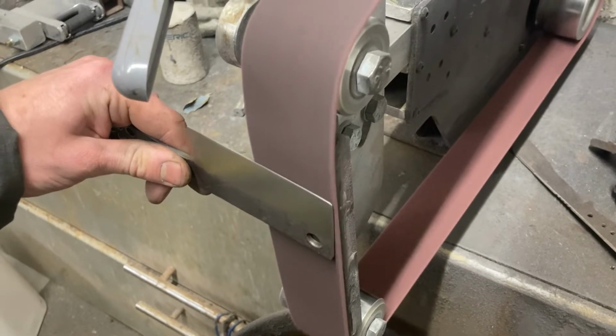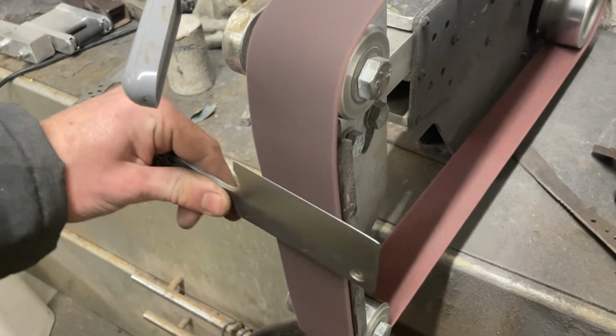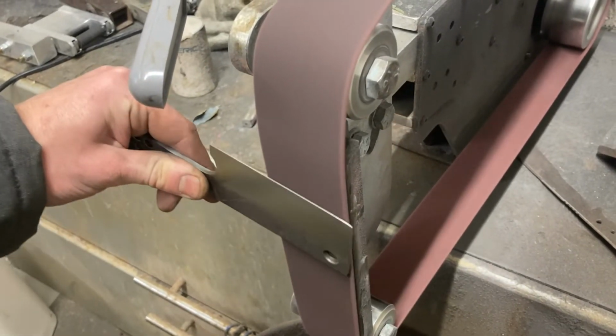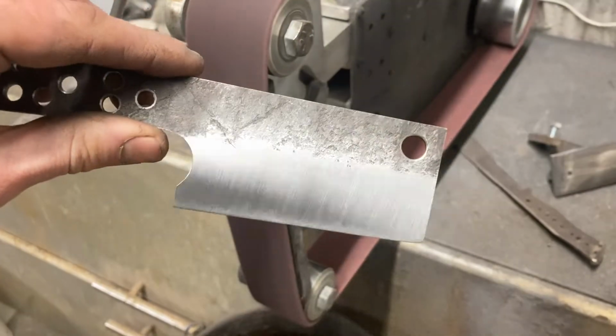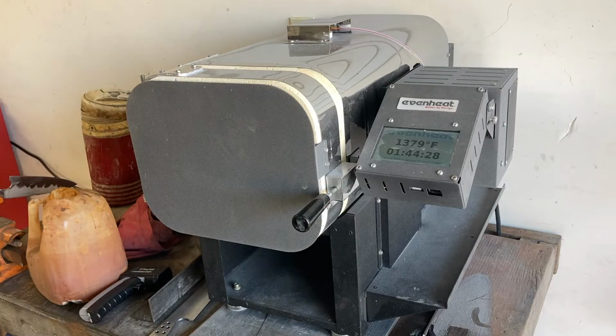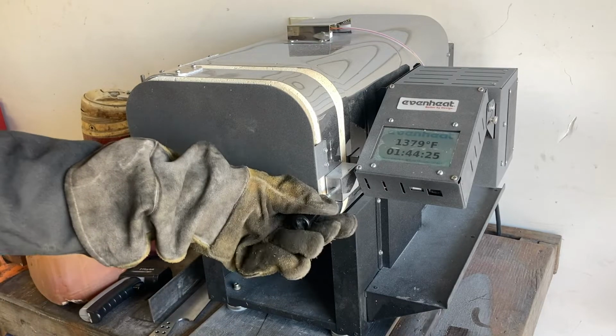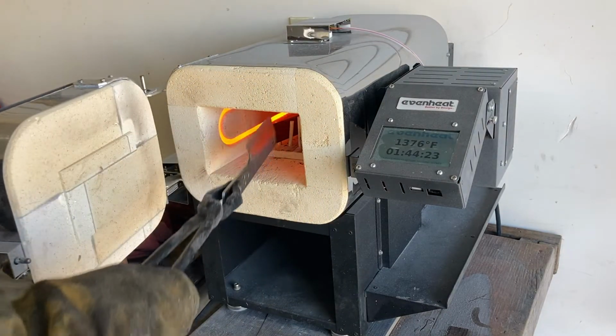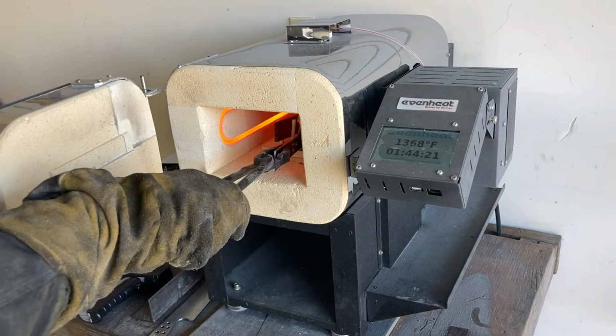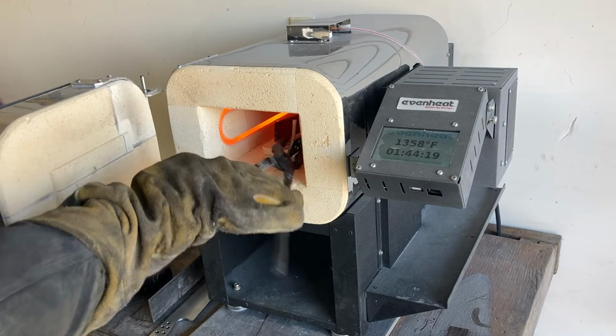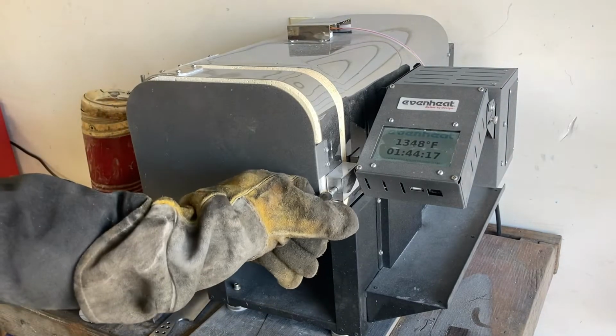Here I'm just putting on a rough bevel before heat treat, just so that I have a little bit less material to remove after heat treat. I'm heat treating this at 1475 degrees inside my even heat kiln, and then once it's up to temperature I hold it there for around 10 minutes and then I quench into Parks 50 oil.